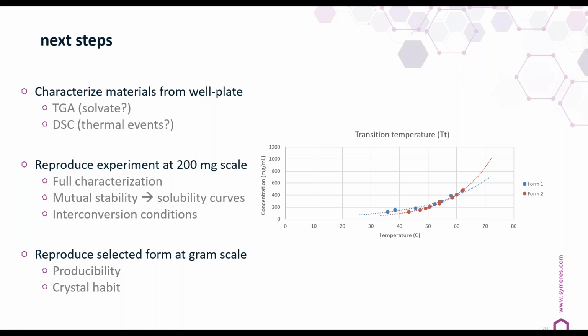Reproduce the experiment at larger scale. That is why we have the different Technobis equipment in-house. You can do a full characterization, you can follow actually what is ongoing there, and you have mutual stability. You can make your solubility curves. Here's an example of two different forms which we found in a screen, and it depends on at which temperature it allows you to crystallize. It is about 55 to 60 degrees, where the transition temperature is, which is a temperature which might occur in crystallization of your compound at high concentration in production, while in your lab you have a low concentration and it starts to crystallize at 50 or 40 degrees. So you come up with the wrong form, as it is a different stability there.